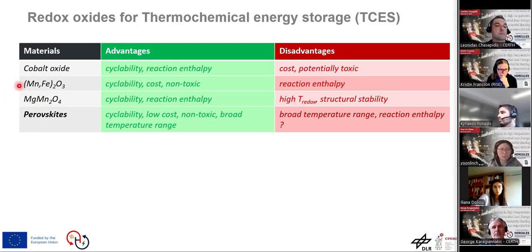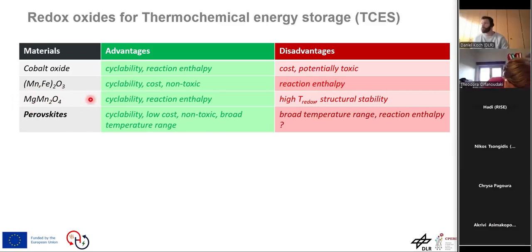Oxides based on more abundant and cheaper elements, like manganese-iron mixed oxides, are also cyclable, of lower cost, and non-toxic, of course, but the problem is that the reaction enthalpy is not as high as that of cobalt oxide, for instance. Other combinations, including magnesium and manganese oxides, perform well on reaction enthalpy and on cyclability. However, they need a very high temperature in order to initiate the reduction and therefore the reverse oxidation reaction, which can cause structural stability issues when these materials are cycled many, many times.